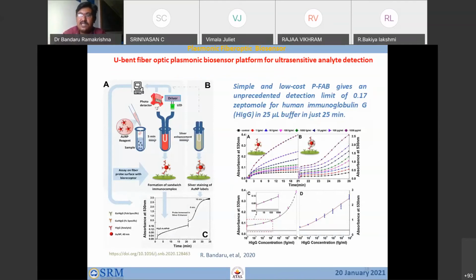And I adapted the immunosensing technology where the ELISA is happening, not ELISA, that the nanoparticle technology is happening. LSPR is happening on the fiber, and nanoparticles can be used as recognizing elements. And I have reported a very, very low concentration, that is 0.17 zeptomole, or maybe 100 molecules in 25 microliters, is possible to detect within 25 minutes. So this is what I have done in my PhD.